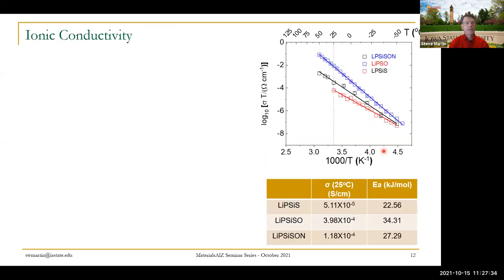Okay, let's move on now to the second part of the talk, and that is some of the electrochemical behaviors. Here's the Arrhenius plot of the conductivity, and what's perhaps somewhat surprising is that you would think as we add oxygen, we would lower the conductivity. In fact, if you look carefully, the oxygen does lower the conductivity slightly here, so the pure sulfide in black in the middle lowers the conductivity initially, but our oxysulfide nitride actually has a slightly higher conductivity as seen here.